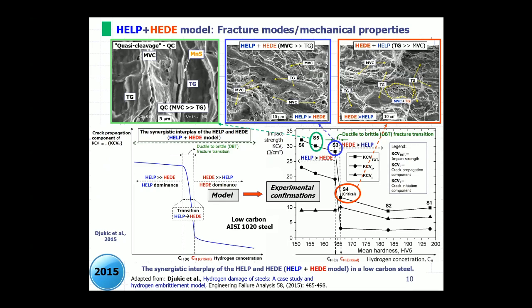And upon reaching the so-called critical hydrogen concentration, we have a more or less sharp drop in mechanical property, which means that we have a macroscopic embrittlement of the material. And if we carefully investigate what's going on with the S3 specimen in blue and S4, S3 still has good ductility and S4 is embrittled. We can see that we have a very similar fracture appearance, which means that we have a ductile failure with microvoid coalescence as a result of the HELP mechanism, and on the other side we have a transgranular failure area due to HEDE, which is a brittle failure.